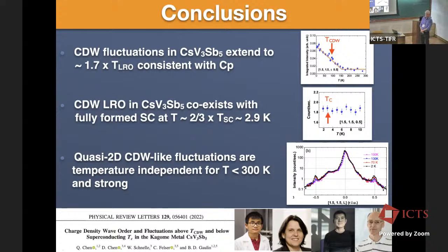So what that means is that the CDW fluctuation you observe below 300 Kelvin, just above, let's say, 100 Kelvin, is something to do with this van der Waals bonding? So what kind of CDW fluctuation are you seeing? Oh, the only thing that we can really tell about the CDW fluctuations is their wave vector. So we know they correspond to a doubling of the unit cell in the Kagome plane, and in this case, a doubling of the unit cell along the stacking direction. But that essentially never changes.